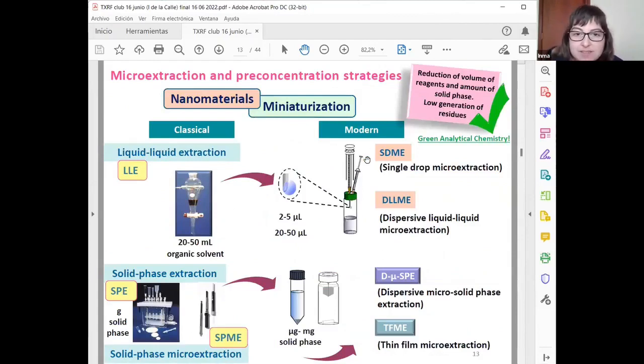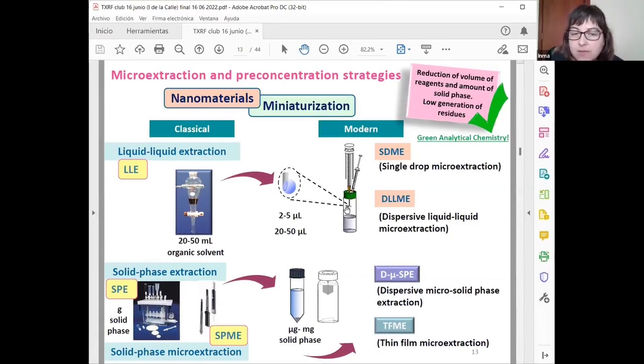In relation with the single drop microextraction, there are different modalities. We have the headspace mode. If we have an aqueous sample, we can use this mode. However, if we have an organic solvent which is insoluble in the sample phase, we can immerse the single drop directly into the sample solution. So it depends on the analyte. If it is organic or inorganic, we need to select the proper solvents to perform this single drop microextraction. We didn't have any work using this technique for TXRF. I think Eva has some publication on this with trichloro, I don't remember exactly, an organic solvent, trichloromethane or something like that.